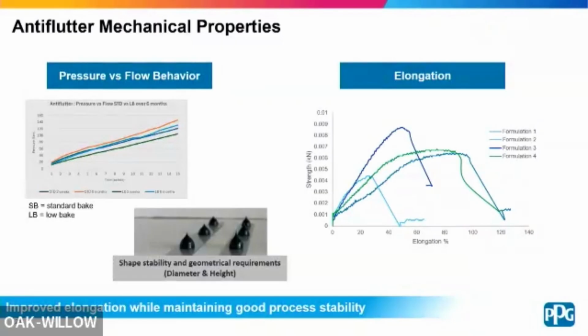And then on the elongation side, so this is just, again, that tensile test I mentioned, so we're showing strength versus elongation percent. You can see our initial formulations, we were maybe in the 20% elongation range, able to tune that up to 80 to 100% elongation, depending on the specific technology. So we were able to get that improved elongation, but while maintaining that good process stability as well.